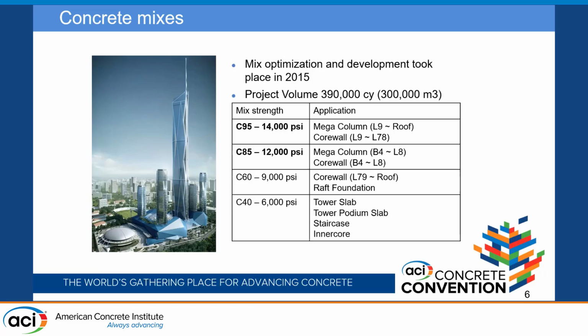And it's important to point out that the raft foundation was poured in 3 castings, and the volumes ranged from 5,200 cubic yards to 13,000 cubic yards. On one particular pour, a 12,800 cubic yard placement, it was done in 28 hours with 9 pumps and 120 mixers.